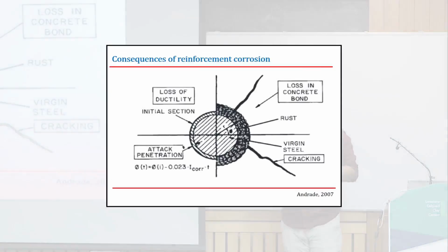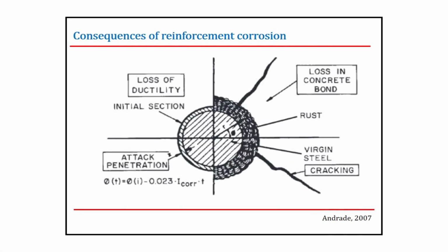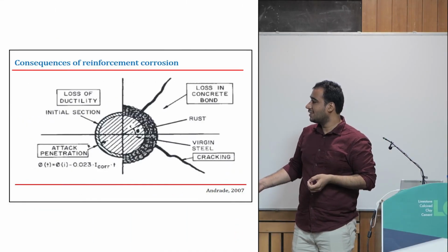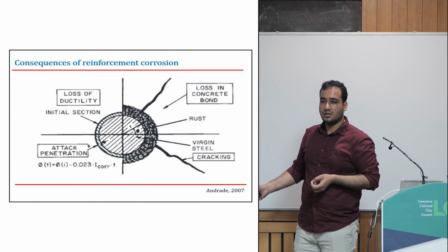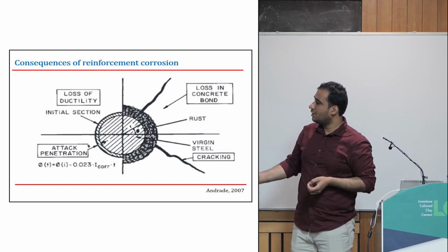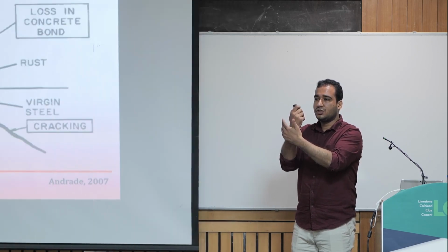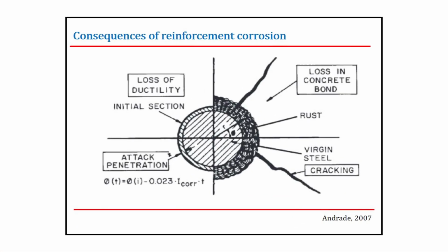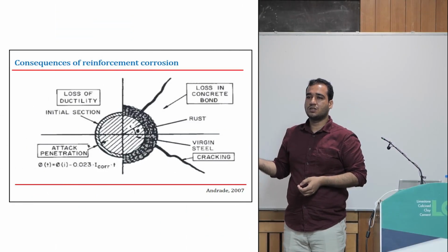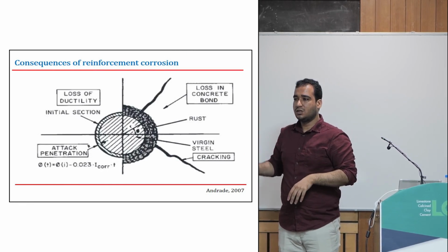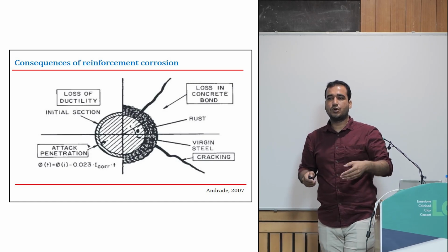So, to summarize, what can be the consequence of this destruction of the passive film in corrosion? Initially, the penetration attack starts. You start to lose your rebar diameter and rust starts to form. The rust will lead to the generation of voluminous rust product, and the loss of iron. This will start inducing tensile stress into the concrete and you will start to have cracks. These cracks will lead to the loss of the bond between your rebar and the concrete. So the distribution of the stresses which happened through rebar to concrete due to the bond development, you start to lose that. And when you start to lose that, the collective effect of this and the penetration attack, the loss of the rebar, you start to lose ductility of your structures. And sometimes you see a sudden collapse of the structures. These are the critical consequences when you ignore corrosion in a structure.